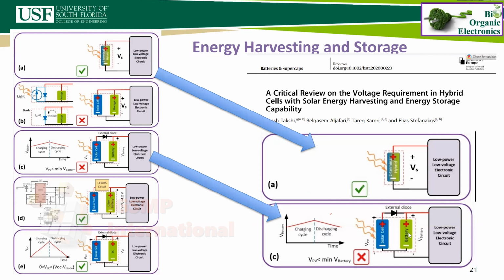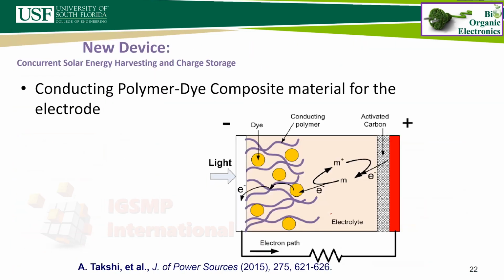And that's not necessarily solving the problem that we have for designing low power, low voltage electronic circuits with a hybrid device. What we truly want is something we call a two-terminal device. So a single electrochemical device that can behave both as energy storage and as energy harvesting from photons. And that led to the next idea: looking at the similarity of the structure of the supercapacitor and the dye-sensitized solar cell, we can combine them by having a porous electrode, activated carbon, as a counter electrode. And instead of using titanium oxide, we use conducting polymers, which have the ability of pseudocapacitive behavior. So assuming that the light is absorbed by the dyes, we can transfer the charge to the conducting polymers, but this would be more like a pseudo-supercapacitive storage.